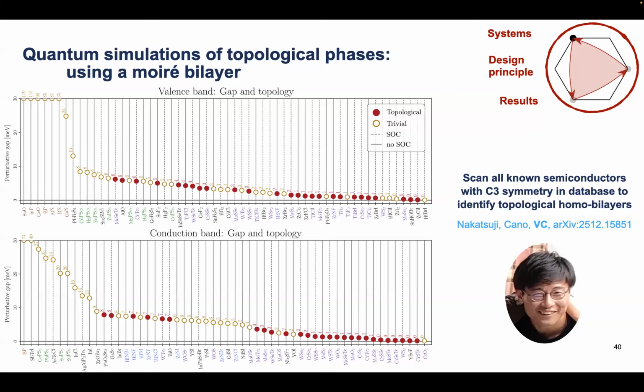I noticed that you have lots of topological materials at small gap. Yes, but small gap materials are extremely sensitive to disorder. Does it make sense? Basically, all of those topological materials with zero gap, I wouldn't even try to use. Whenever you have disorder, I don't know what you would do with those materials. And there's a lot of disorder in those twisted structures, maybe not at a 5-degree twist angle. So I would advise anyone doing an experiment against choosing those ones. But this serves as a guide.